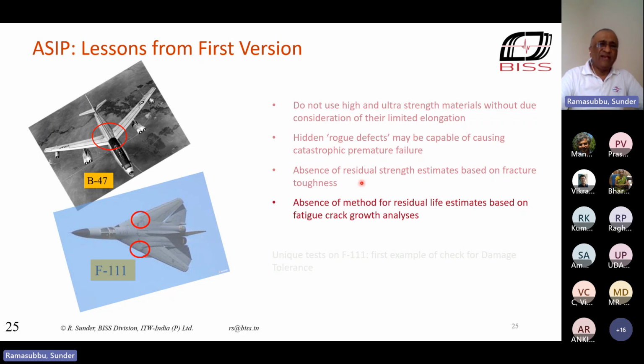But out of every lesson, something unique, something special comes out. So I would say fracture mechanics in the aircraft industry really took off with a bang because you needed to know what will be the tolerable defect. You learned about the importance of detecting defects in manufacturing and in inspection in service. And importantly, very importantly, because that's where I have spent my lifetime, you start learning how to compute the life of an aircraft between the time a detectable crack appears to the point when it's going to lead to catastrophic failure. But there was one extremely unique feature that came out of this lesson, out of this mistake.